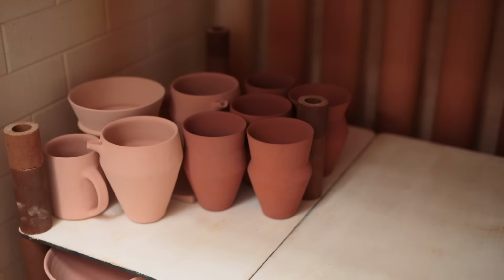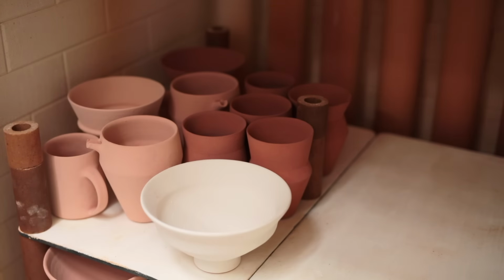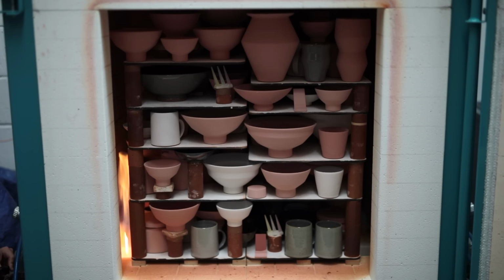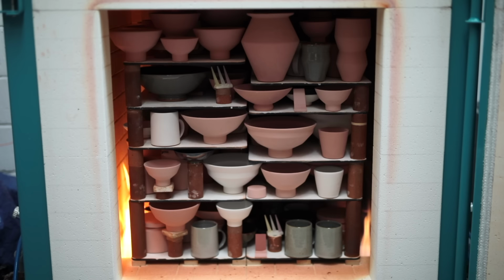For this gas reduction firing, the pots cannot touch, otherwise the glaze that coats them will stick them together, so typically I leave about 2 to 3 millimeters between each. Yet I still want to pack the kiln as densely as possible, as not only does it of course make each firing more cost efficient, but it also makes firing in a reduction atmosphere easier, as there's less space for air to take up, as if there is a large open void within the pack. It can be tricky reducing it evenly.